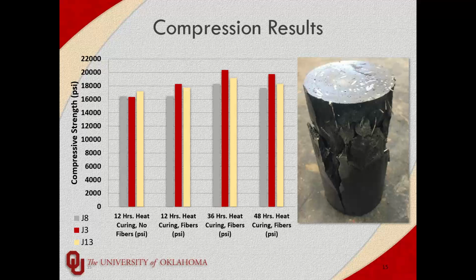The one thing we did notice is that heat curing seemed to be much more effective with the steel fibers as opposed to without. And I think that has something to do with the steel fibers being able to radiate the heat inside of the material a lot more effectively, as opposed to an unreinforced UHPC with no fibers, where the heat just has to traverse the cross section to get to the center. Because these fibers tend to touch and collect, they'll send the heat to the inside of the cylinders much faster. So you get some benefit with the heat curing using those fibers.